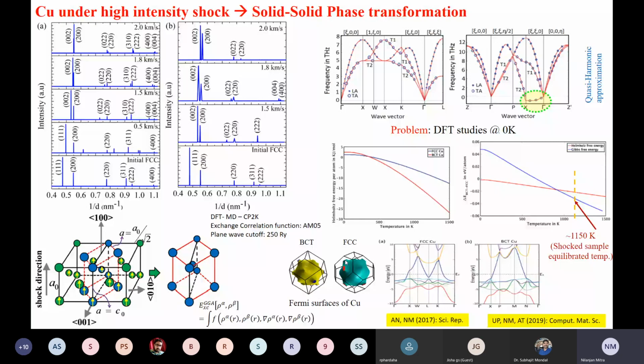Now, when you do those kinds of things, obviously you have to do something called X-ray diffraction. X-ray diffraction is also a very common methodology. We have done it numerically, but you can also do it experimentally. We have obviously validated our work with experimental investigations. And when you do this XRD, what you basically probe is the different types of planes along which the light will reflect back. Based on those, you can find out that the material exists in a particular orientation, or has a particular space group.